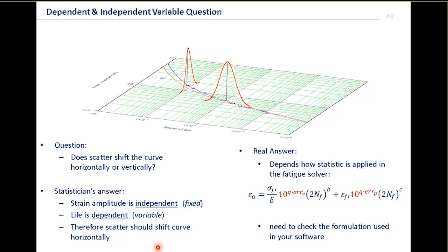In fact, when you do an SN analysis, that's exactly what we do. We move the curve left to right in terms of its reliability statistic. However, in strain life, we move it up and down. And the reason we do that is because the strain life equation, the Coffin-Manson-Basquin equation, is a transcendental equation. We can't rearrange it in terms of NF as a simple function of strain. So in this case, we apply a separate scatter factor effectively on the plastic and the elastic sides, and that effectively moves it up and down.